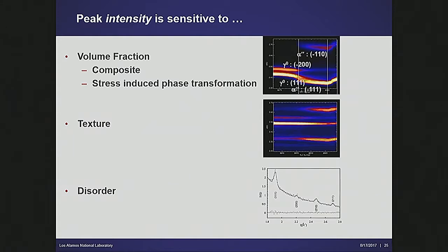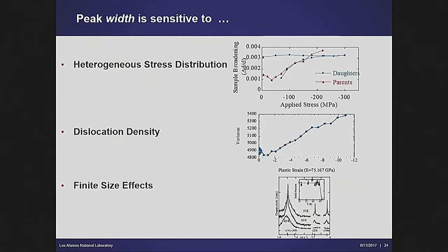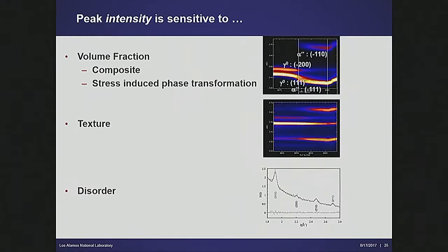And of course, in the diffraction pattern, you can also pull information out from the peak intensity. In a composite, different phase fractions, you've got texture, which is a huge deal, and disorder. I think as we go along, you might naturally say, well, what are the problems for which a reactor is better suited, and what are the problems for which a spallation source is better suited? Considerations about position and width and intensity and how much information you get out in an individual measurement all relate to that.